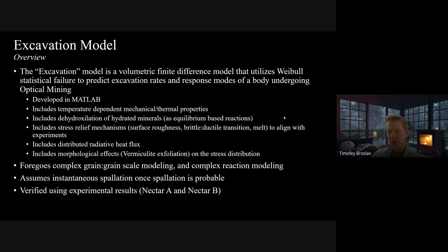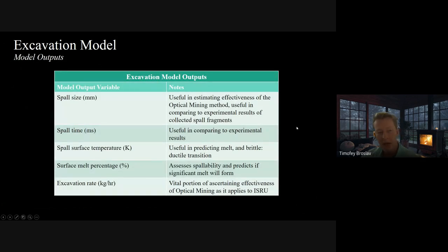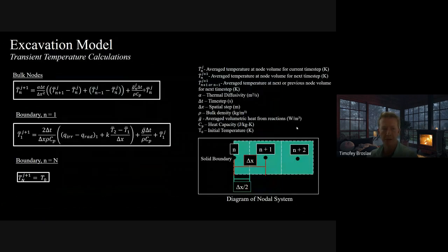Furthermore, morphological effects like vermiculite exfoliation were also included and their effects on the stress distribution. So this model forgoes complex grain-to-grain scale modeling due to its inclusion of Weibull statistical failure. It assumes instantaneous spallation, and it was, like I said, verified from experimental results. The main outputs of this model were spall size, the time to spallation, spall surface temperature, the melt percentage of the surface, and the excavation rate in kilograms per hour.